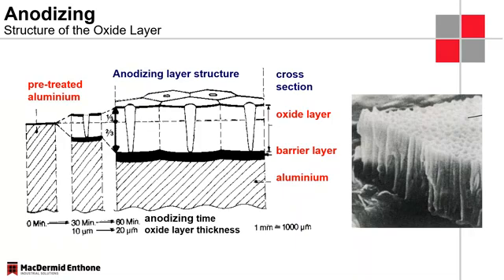After a few minutes, we'll see this aluminum oxide layer growing into the component, and because of the volume increase, it will also grow outside of the component, and it will actually increase in dimension. And what we normally say, up to a certain plating time, we'll see an increase of the component dimension of about a third. So 2/3 of the anodized oxide layer will actually go into the component, and about 1/3 will grow outwards of the component, and therefore increase the dimension of components.